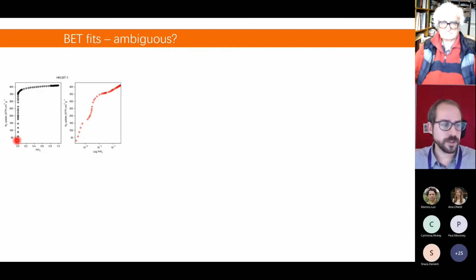If I take one material like HKUST-1, you can say, well, it's very easy because I just need to fit BET probably into this range of pressures. The problem is that if I really look at the isotherm on a semi-logarithmic representation, this is not a typical type 1 isotherm. And what you can really see is a combination of different phenomena taking place during the adsorption process of nitrogen. What we know is that we are filling different adsorption sites with different energies, and this is why you see all these different steps in the nitrogen adsorption isotherm, which is something that you very rarely see in an activated carbon, but it's quite important to highlight for these metal-organic frameworks.